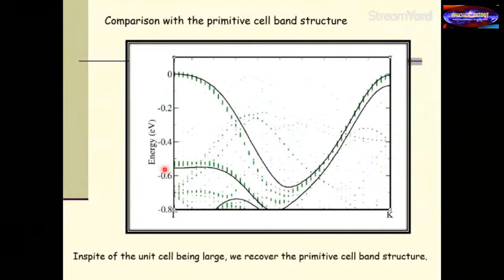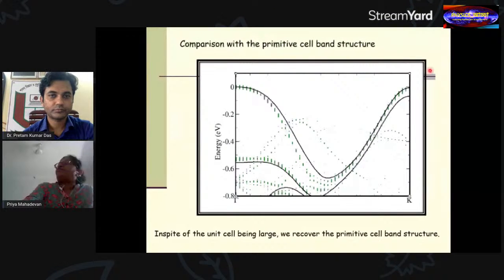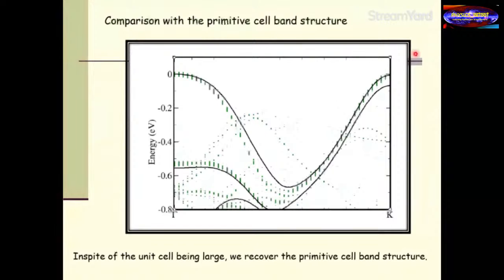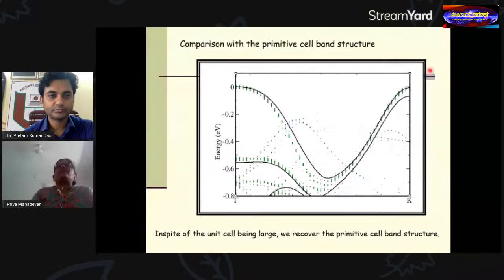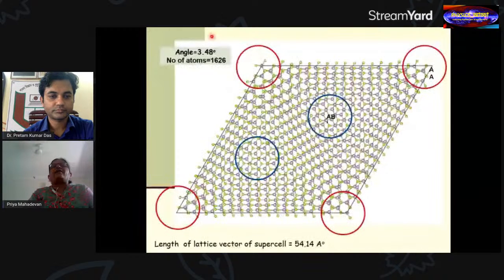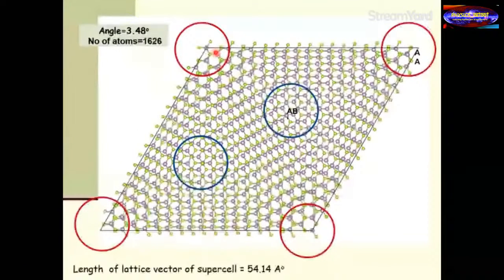So is this true for all systems? But we know that people have seen some other systems, with twist angles, 4 point something degrees. So we took one such angle, which had a similar number of atoms, 1626 atoms, and a similar sized unit cell. Okay, so one thing you would see is that at twist angles, there's something additionally coming in.